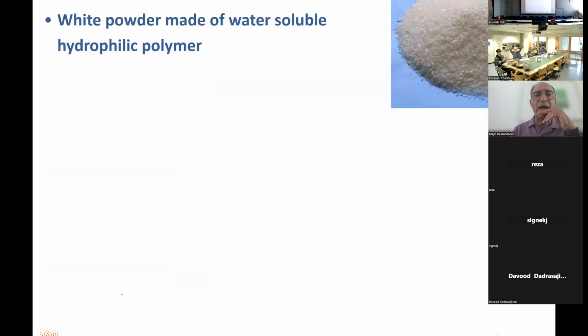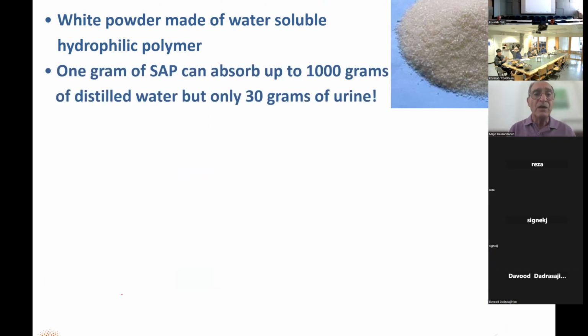And the absorption happens by use of a material called superabsorbent polymer, SAP. It's an extremely hydrophilic polymer. Water goes in there in huge amounts. You're talking about a gram of SAP absorbing up to 1,000 grams of distilled water. And of course, if there are solutes in there, less will be absorbed. In the case of urine, 1 gram can absorb 30 grams of urine.